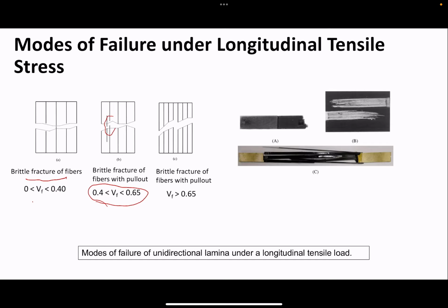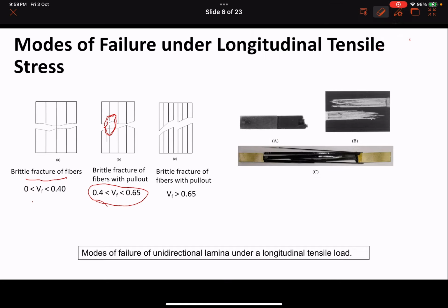What does pull out mean? This is what pull out means, not this one, just this second fiber. If you see, it is outside, or even the first 2. The first is just fiber fracture. Let me not draw, maybe that will make it better. So the first one you can see, this is just brittle fracture. But the second one you see is pull out, because you can see that the fiber broke and then got pulled out of the resin, so there's a void in the resin. So this is the most common type of failure mode.